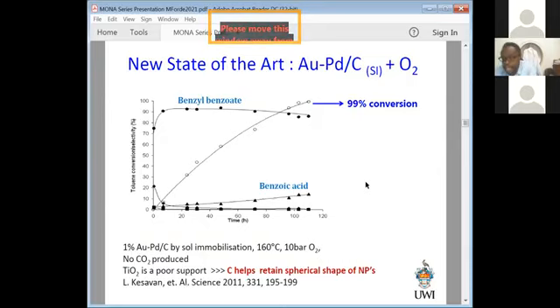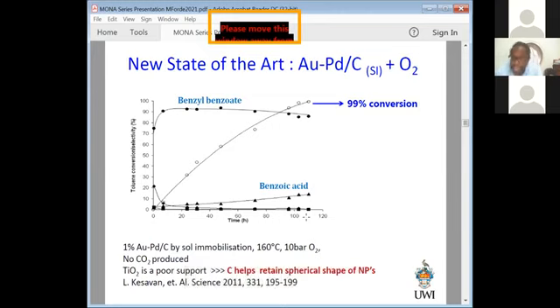And they developed gold-palladium catalysts for this reaction that worked at lower temperature, low oxygen pressures, did no decarboxylation reactions on the product, and so it's atom economic. In this case, conversion was 99% after about 100 hours, but this is known to be a slow reaction. 99% is pretty high, especially with a very high selectivity to benzyl benzoate. Now, benzyl benzoate is an ester that comes from the benzoic acid plus the alcohol or the aldehyde. And there are obviously other pathways in which you can get the benzyl benzoate as well.